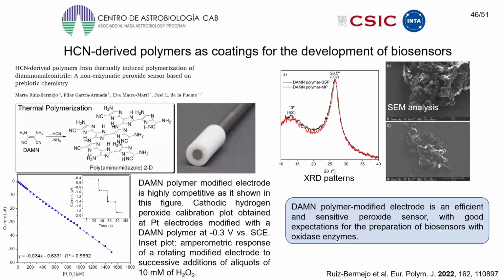Additionally, the polymers synthesized using the tetramer of hydrogen cyanide, diaminomaleonitrile (DAMN), were successfully used to modify electrodes. These polymers were synthesized under dry conditions in bulk, mimicking early Earth thermal environments. The resulting black solid, like this, resembles carbonitrides. Electrodes modified with DAMN polymers present good redox properties, especially those synthesized by melt polymerization. These modified electrodes demonstrated promising potential as a biosensor.